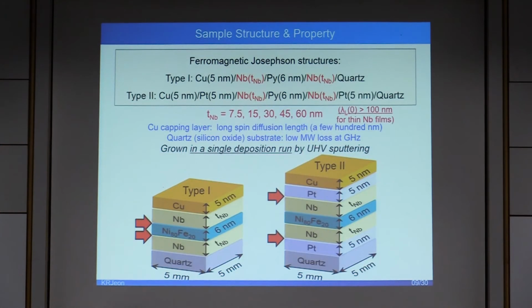In the following, I will present a systematic set of temperature-dependent FMR measurements on niobium-permalloy-niobium trilayers with various niobium thicknesses, and show that, as expected, spin transfer from the precessing permalloy into the niobium layer through quasiparticle excitation is blocked at low temperature by the superconductivity. I then extend the FMR measurement to platinum-S-F-S-platinum structures, in which the platinum layer provides an effective spin sink with strong spin-orbit coupling. When the platinum layer or other large spin-orbit coupling spin sink is present, significantly enhanced FMR damping below Tc for niobium layer thicknesses of the order of the coherence length is interpreted as evidence for the generation of superconducting pure spin current.